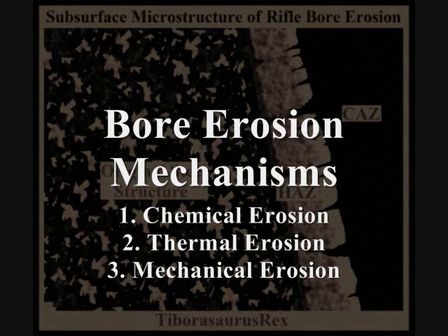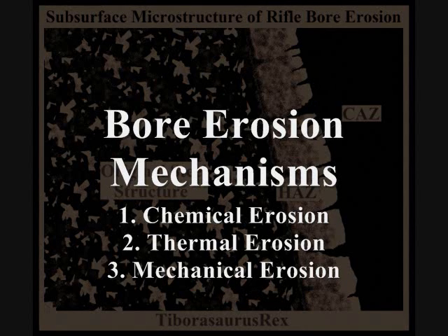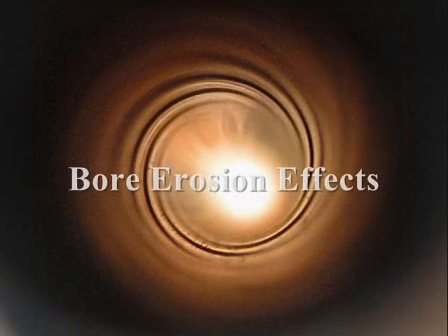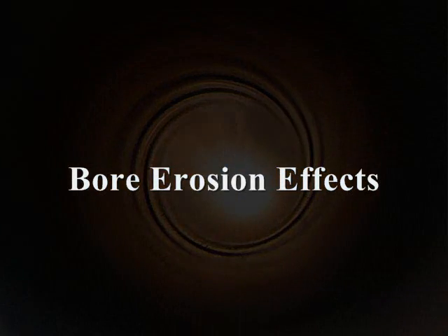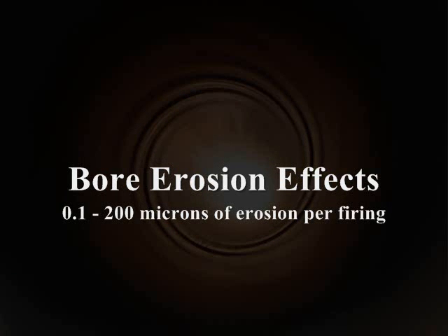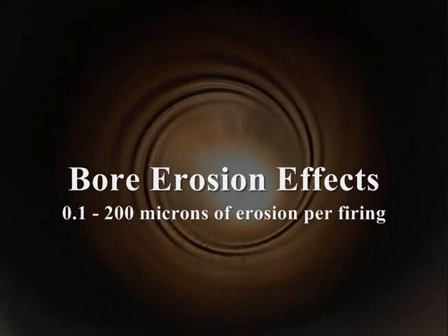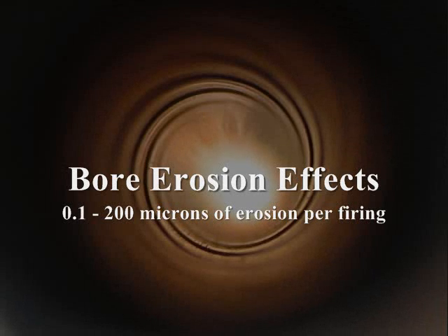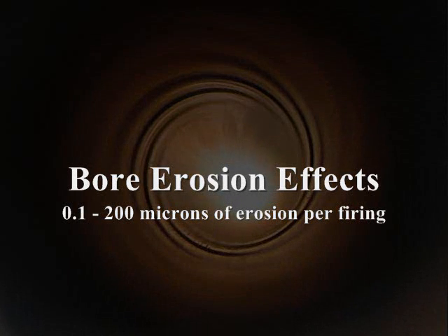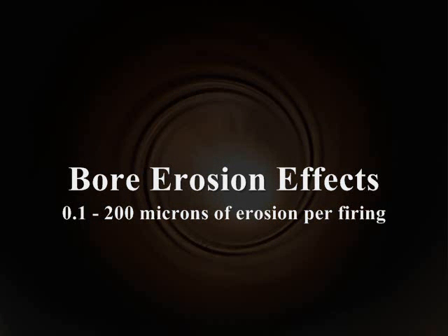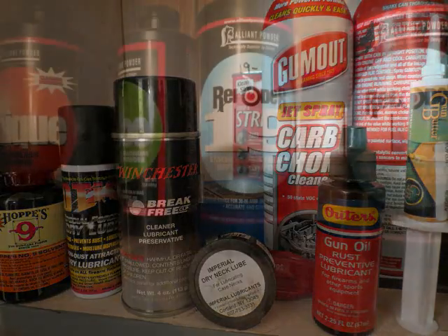As for the effects of bore erosion, per shot you might only have maybe a tenth of a micron, or you could have up to 200 microns of bore erosion per shot. That's how much material would be removed from the bore each firing. So you have a huge range of how much this can affect it, from a tenth of a micron to 200 microns. Now, a micron's pretty small, so you're still going to have a couple thousand rounds of service life, but it tremendously depends on how you treat your bore: the cleaning regime you use, the chemicals you're going to subject it to, the gunpowder recipe, and a lot of it depends on how hot your cartridge is loaded.